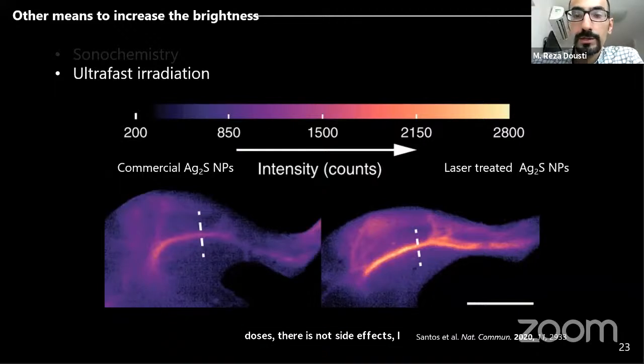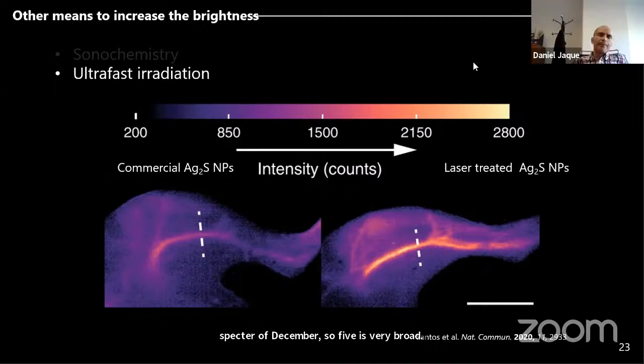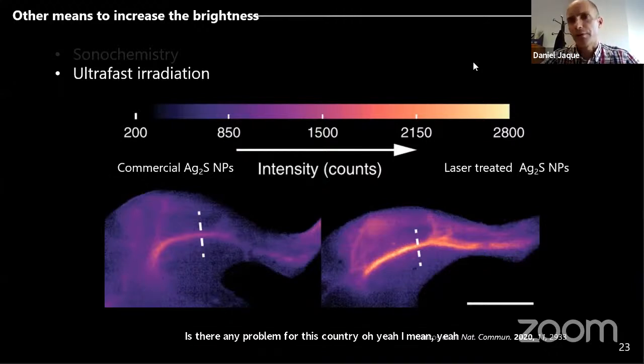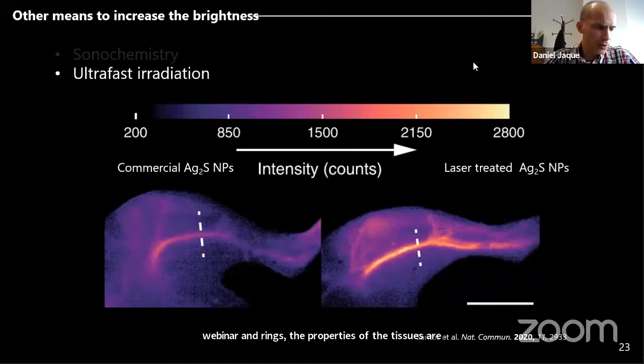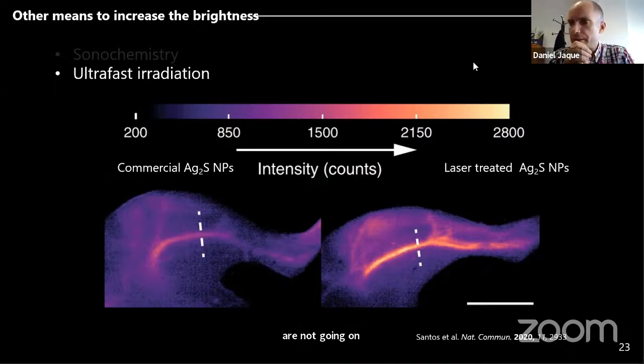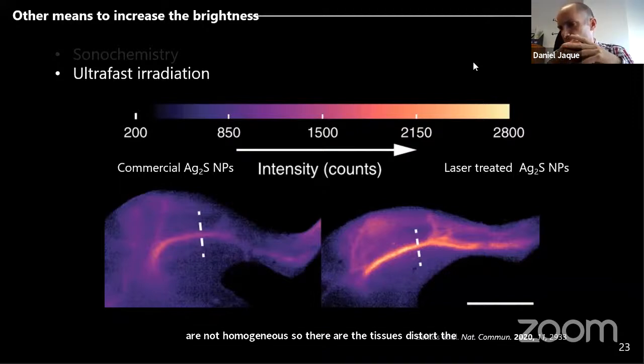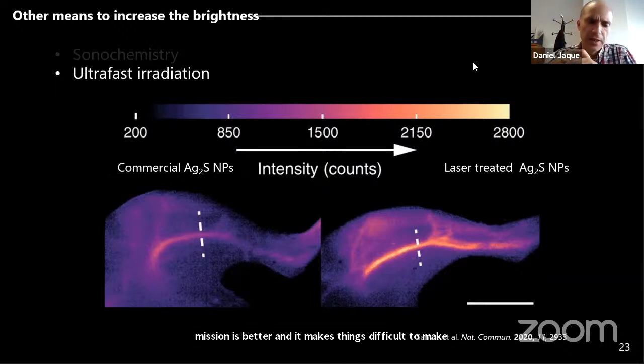Thank you very much. Just to control the time, one more last question that Professor Carlos Jacinto is asking. Thinking in biological applications, the emission spectrum of the silver sulfide is very broad. Is there any problem for this material? Yeah, it would be better to have a narrow spectrum, because when you have a very broad spectrum, in this very broad wavelength range, the properties of the tissues are not homogeneous. So the tissues distort the emission spectrum. This makes it difficult to make a good interpretation of the results. So it would be better to have narrow emission lines, because you can optimize the system, and you can be very sure what you are measuring.